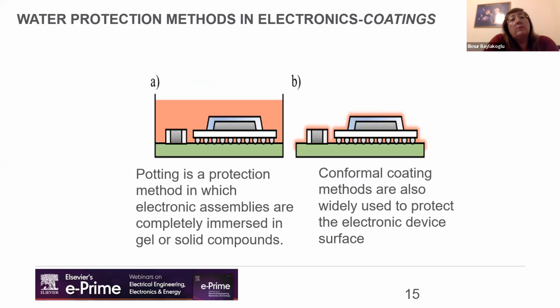Another method that is mostly used is coatings. We try to protect our electronics by using some special coatings like potting or conformal coating. In potting, all the assemblies are completely immersed in a gel or solid compound, which is mostly used especially for vibration environment applications. And conformal coatings are widely used to protect the electronic device, only on the surface of the electronics. These can be some epoxy resins, some urethanes and silicone gels.